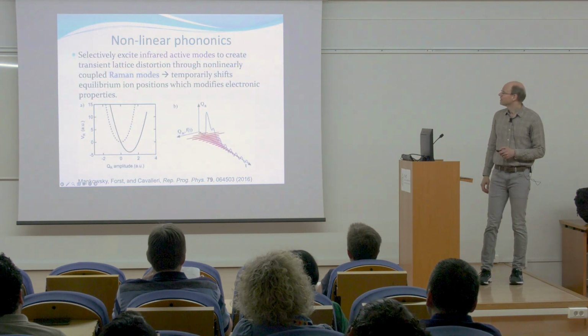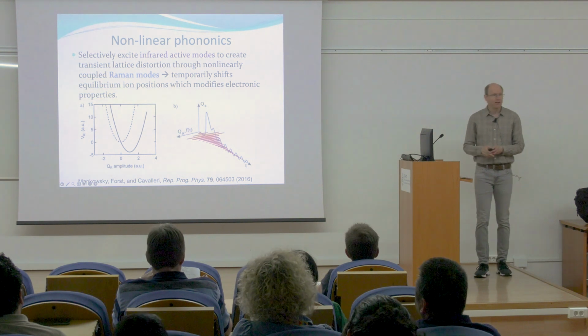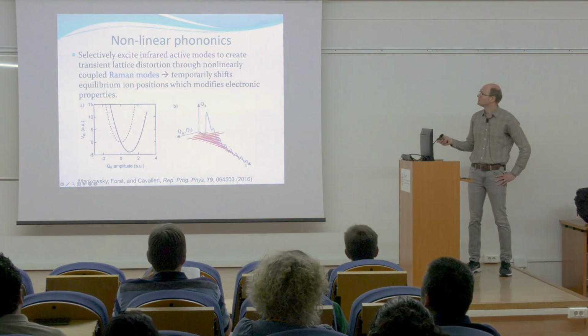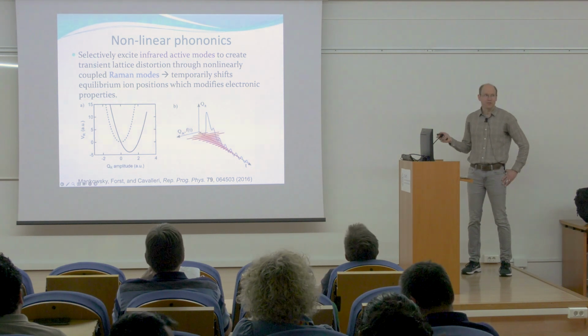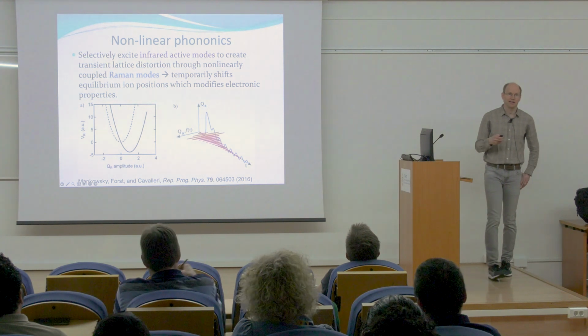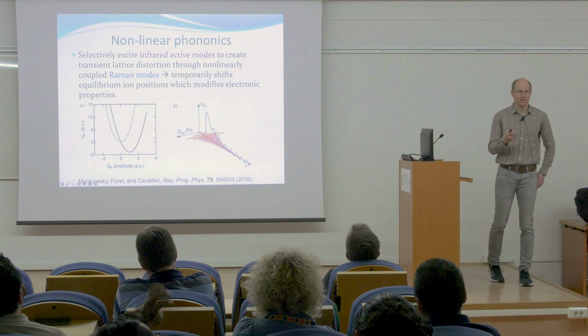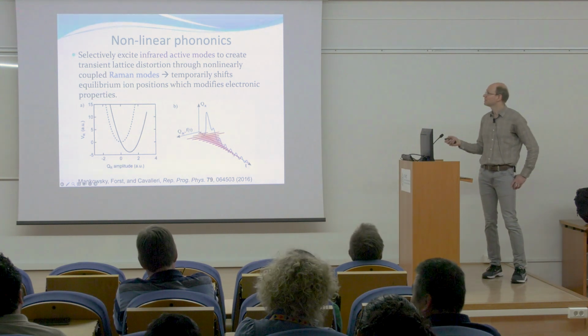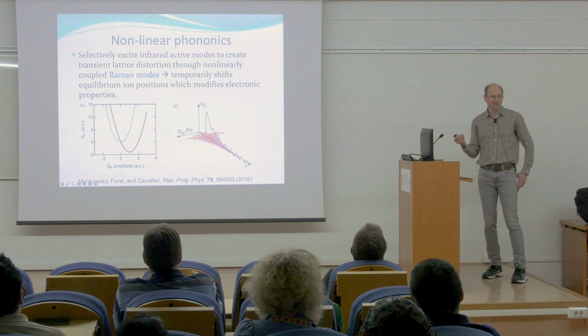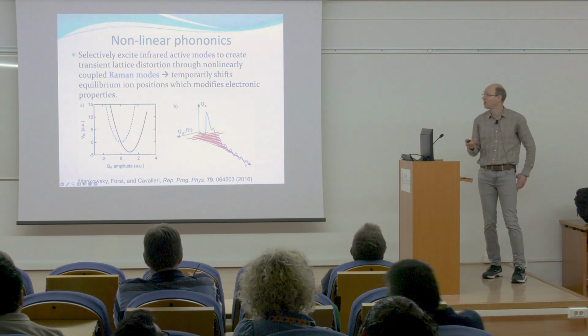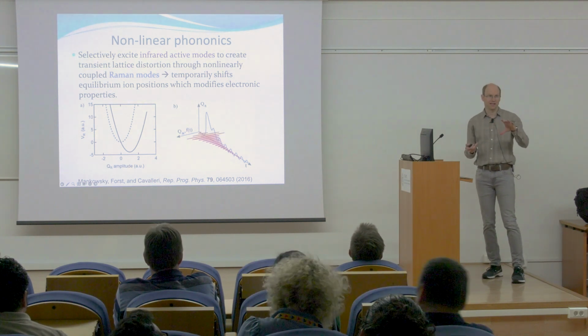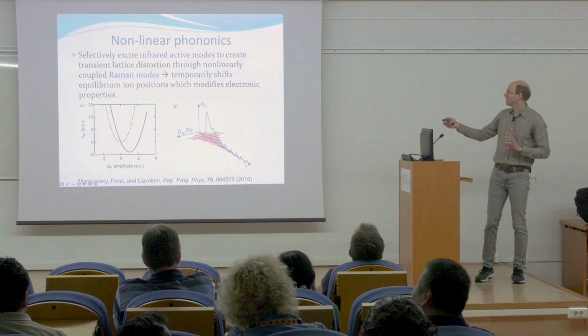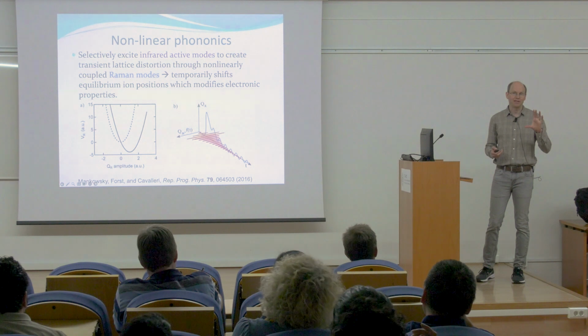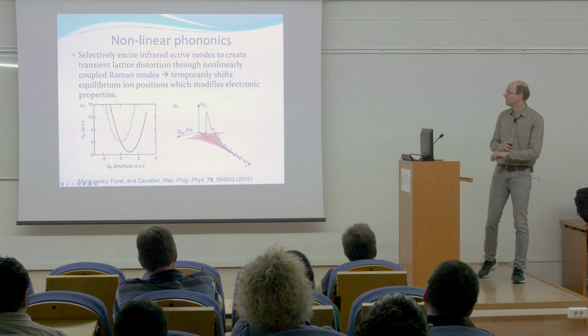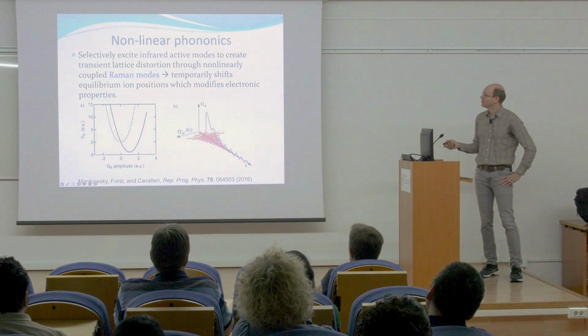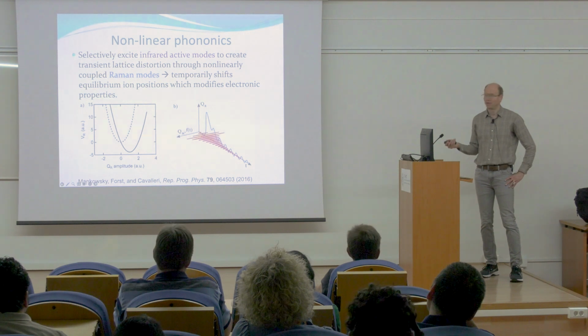Okay. So now I want to come to one of the topics that we've been working on a lot in my group, which is nonlinear phononics. So the examples that I've given up till now have mainly focused on light that is tuned to energies where the electrons are excited. But now we could switch gears and we could ask about light which is tuned towards energies where the phonons are primarily excited. So they're not resonantly coupled to the electrons, especially if the system is electrically insulating, then there's a gap. And if the light frequency is smaller than the gap in the system, then I don't have enough energy to create any electron excitations. There's only enough energy to excite collective modes like the phonons in the system or maybe magnons.